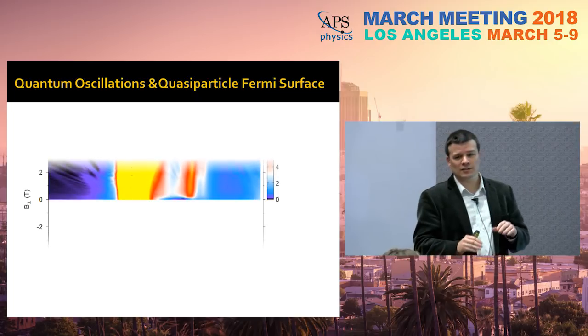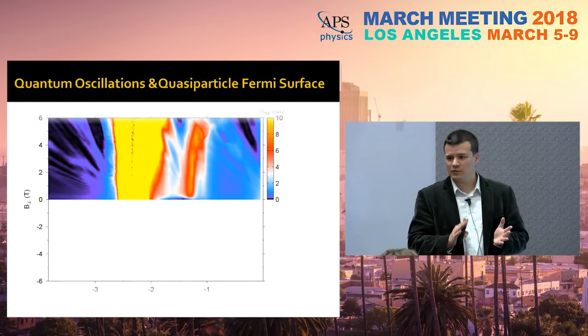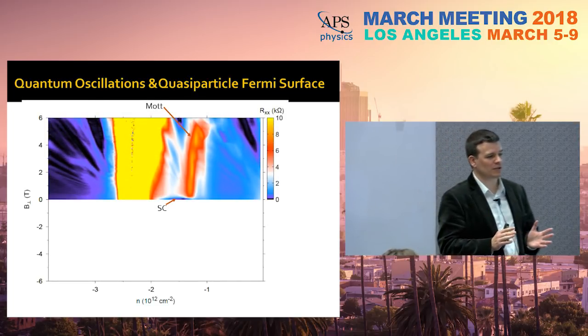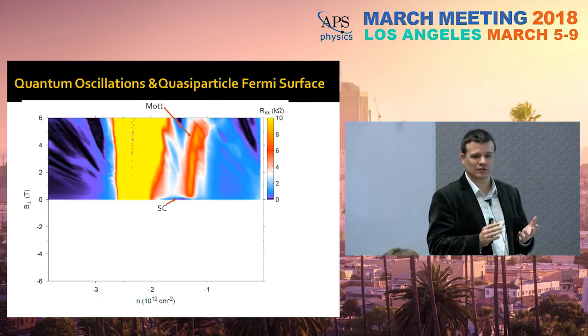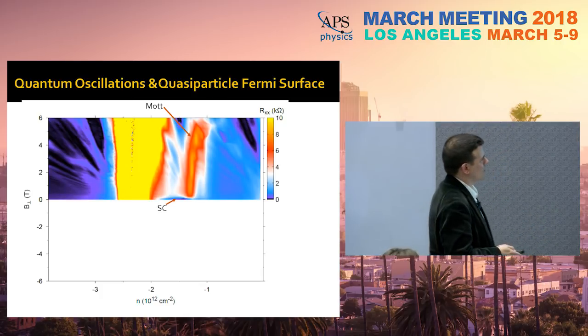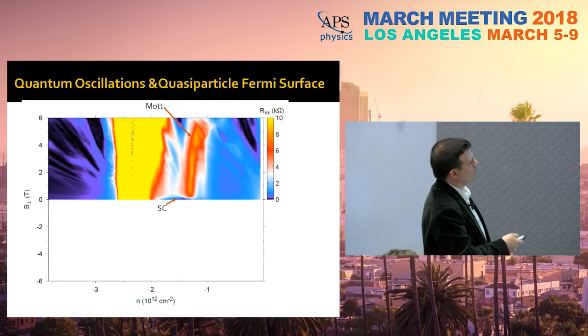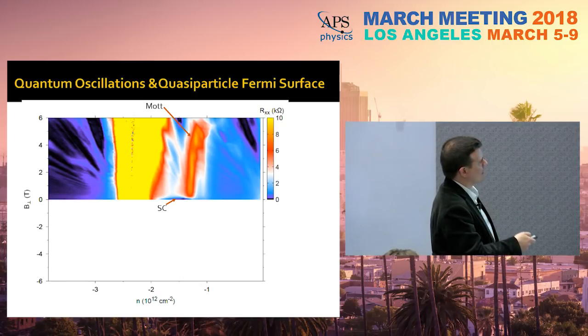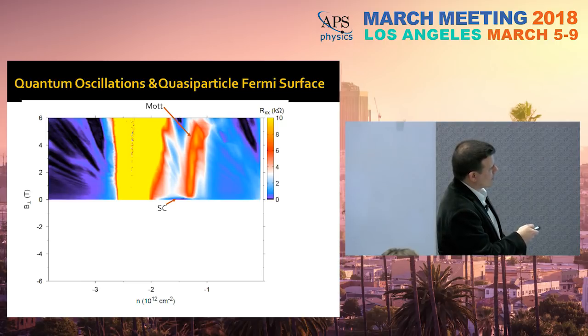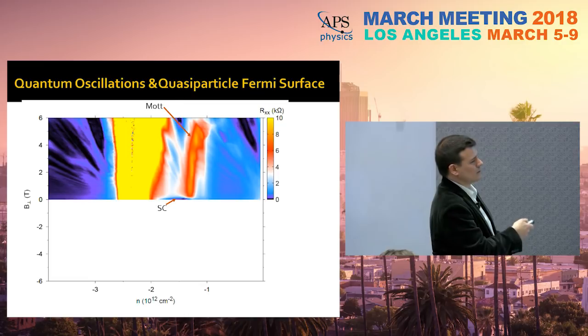Graphene is a very high quality system, highly crystalline with high mobility. This means that we can measure quantum oscillations, Shubnikov-de Haas oscillations, in the system continuously as a function of gate voltage. So in this plot, I'm showing the resistance as a function of perpendicular magnetic field and density. You can see here the superconducting dome at small magnetic field. This is the trivial insulator state for holes, okay, when you completely fill the band. This is charge neutrality. This is the Mott insulator state at half filling.